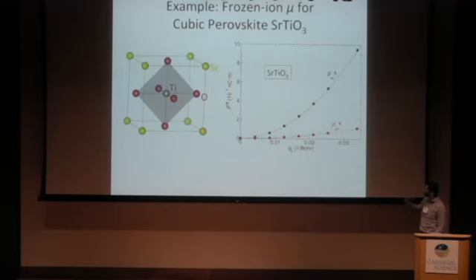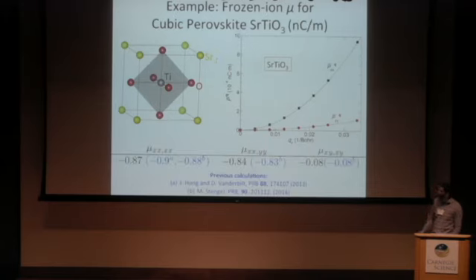So this is an example of a calculation. We have induced polarization versus Q. We can take the second derivative of these curves, this polarization in the x and the y direction, and therefore obtain the clamped ion flexoelectric coefficients. Compared with previous calculations, which are highlighted in blue, we have very good agreement.